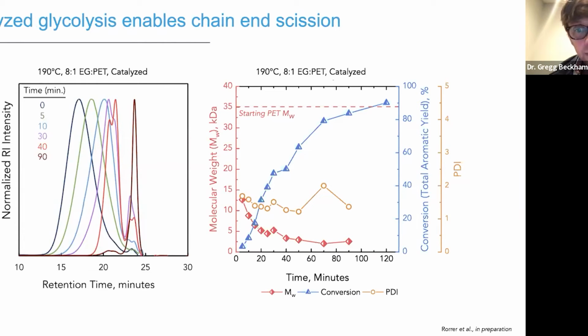This is work that we're doing with Linda Broadbelt's group. She's a world leader in kinetics modeling for polymer synthesis as well as polymer deconstruction. Taking the data on the left-hand side of the slide, which are these gel permeation chromatogram or molecular weight traces of PET, we're able to then plot this in terms of molecular weight, MW, as a function of time.